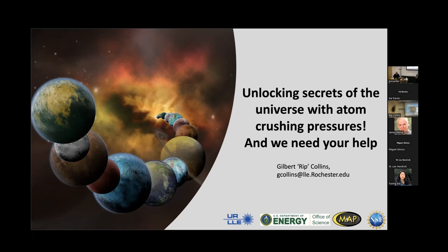So we were doing some work in single crystal diffraction. We were lucky. We were squishing things along one axis that happened to allow this transformation for iron. Sometimes you just never know how lucky you are. So we were reporting this in a number of journals, and a group from Oxford, who we collaborate with all the time, hadn't been able to recreate it. They were also looking at single crystals. This is Jim Harlack, who did some very beautiful experiments for his thesis, but could never see the crystal structure once it went through this phase transition. And part of it just turns out that if you take any other axis besides the one we chose, it becomes nanocrystalline. You can't do single crystal diffraction.